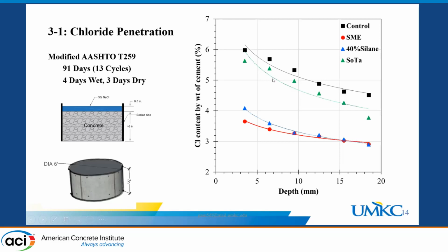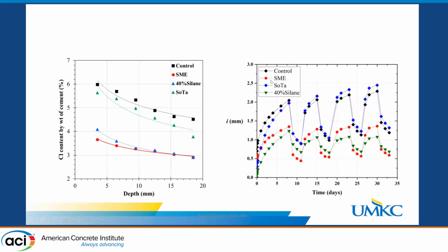So we can see that sodium tartrate was not that effective compared to the untreated control. And as I mentioned earlier, if we look at concrete that fluctuates from wetting and drying, we have more chloride for those concretes, because they have more fluctuation. For concrete with less fluctuation, less absorption and less drying, we have a significantly lower chloride penetration.